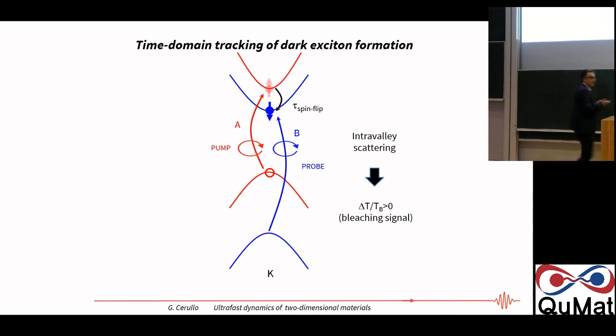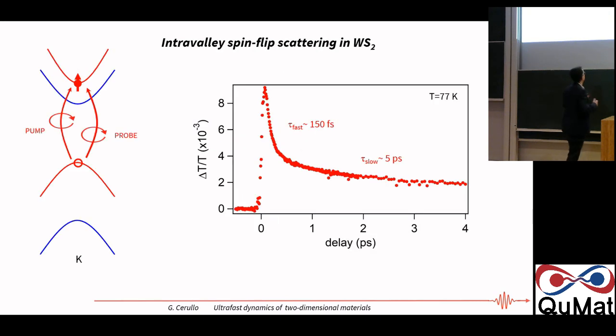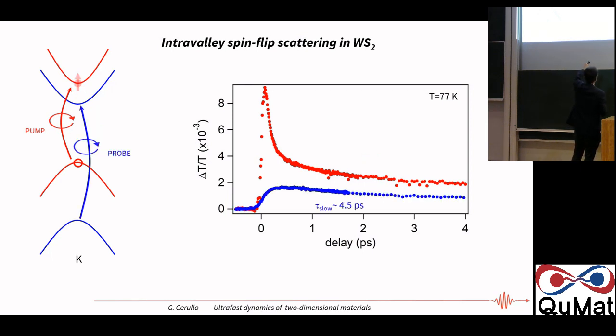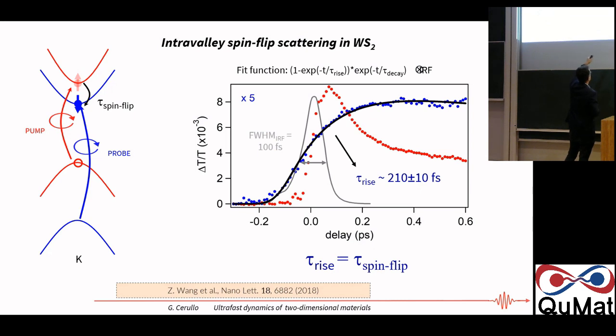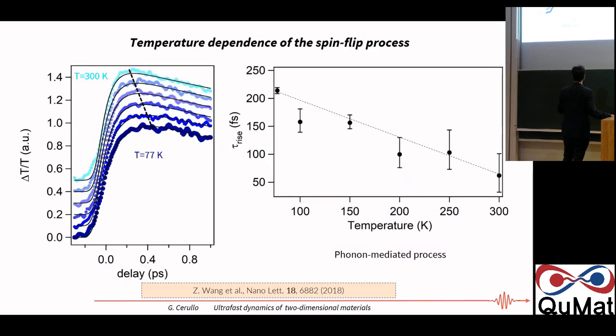So we have to do a two-color helicity-resolved pump-probe. That's what we did. And indeed, we start with the one color and we see the usual instantaneous rise and decay. But now, if we tune here, we see that the rise is clearly much slower. At least if you zoom in, you will see it very clearly. Instead of rising instantaneously with our temporal resolution, it has a delayed rise of about 200 femtoseconds. So we say that this delayed rise corresponds to the time that it takes for the spin to flip. And if you look at the temperature dependence, you see that this rise becomes faster as you go to room temperature. So it's a phonon-mediated process.